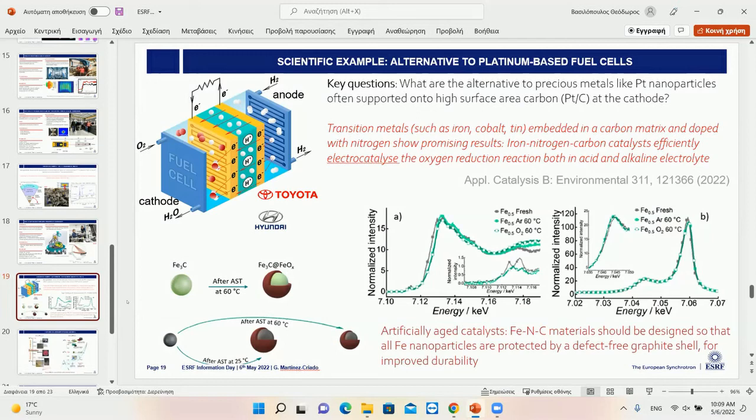And in that context, what was achieved thanks to the measurement of the absorption spectrum of the cathode was the possibility to improve the design of these fuel cells against the artificial aging process. And the message is that iron, nitrogen, carbon material should be designed in a way that the iron nanoparticles are protected by a shell. Its effect is that of a defect-free graphite shell. So